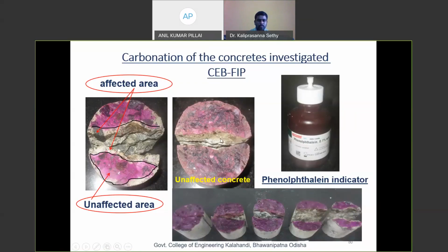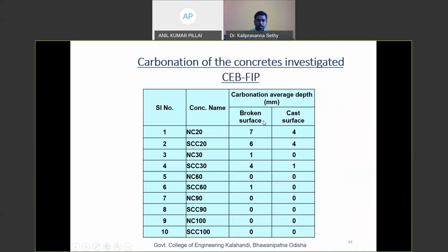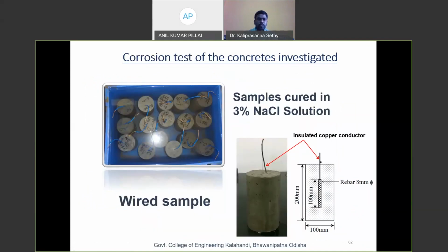So here are the samples which we tested, and these are the readings we observed after putting this phenolphthalein solution. Almost all the samples show very little or zero value, and some show 7 mm, which is very negligible. And you can say it is a very good resistance concrete.